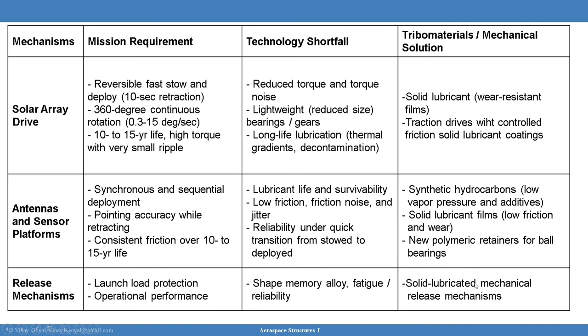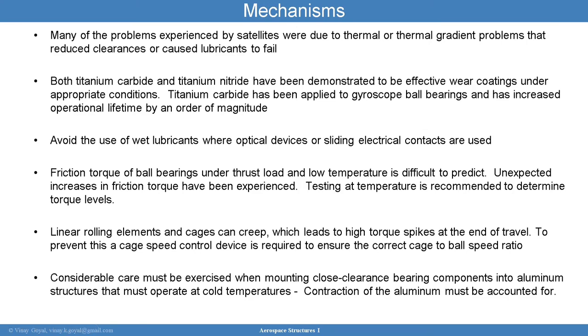For release mechanisms, launch load protection, and operational performance, what we're looking for is shape memory alloy and fatigue and reliability. So that's a shortfall, and the mechanical solution is solid lubricated mechanical release mechanisms. Many of the problems you see in satellites are due to thermal or thermal gradient problems that reduce clearance or cause the lubricants to fail. Both titanium carbide and titanium nitride have been demonstrated to be effective wear coatings under appropriate conditions. The titanium carbide has been applied to gyroscopic ball bearings and it's increased the operational life by quite a bit.